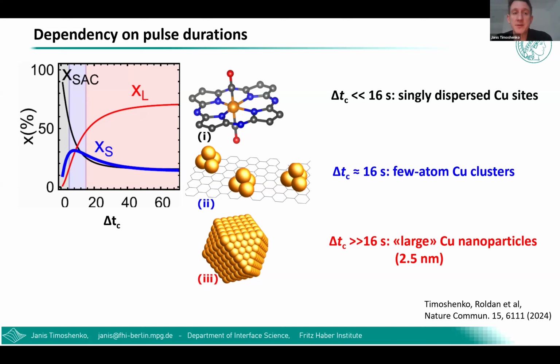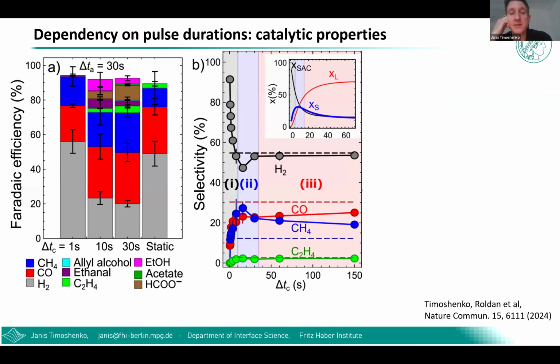So of course, we can now steer the structure of this catalyst, but how does it reflect on the catalytic properties? So we did catalytic performance measurements for this catalyst under different pulse conditions, and we saw very interesting and non-linear changes in the selectivity of the catalyst. So if we apply very short potential pulses, the catalyst mostly produces hydrogen, while under longer potential pulses, it's some combination of hydrogen, CO, and methane that is being produced. But in this interesting regime where we have a contribution of very small atomic clusters, we see quite non-linear changes in the selectivity, and in fact, we see pronounced formation of methane in these conditions.